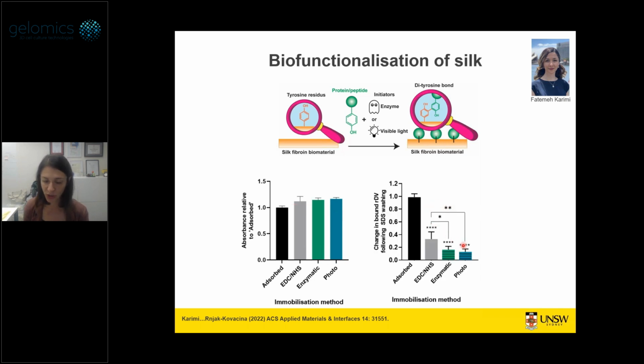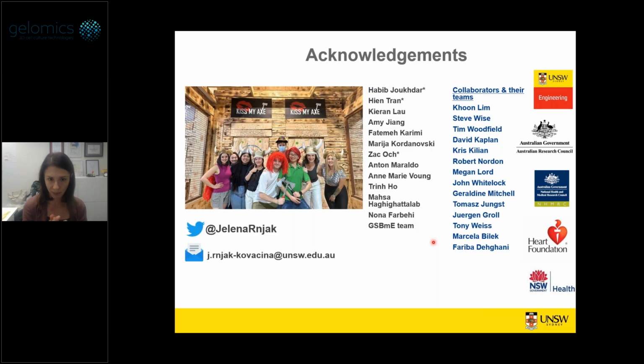But if we actually look at the amount that is lost following strong detergent washes, right? So how much is lost? How much is not covalently bound effectively? We see that with adsorbed, pretty much everything is lost because there's no covalent link. With EDC and NHS, we lose less, but with dityrosine cross-linking, we lose very little of the protein. And that makes sense because we have more amino acids available for this dityrosine cross-linking than in the reactions involved in EDC and NHS. And so with that, I will finish up.